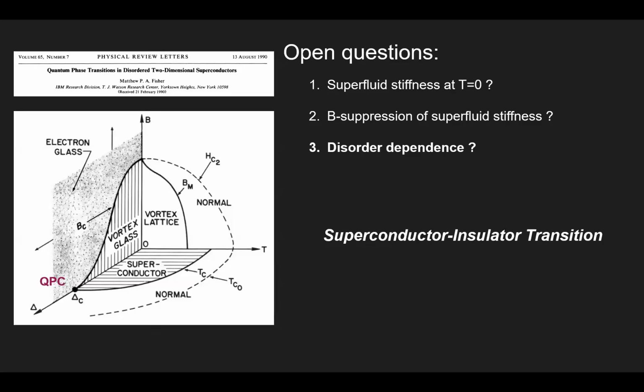And if you look at T equals 0 on the disorder-magnetic field plane, you have this vortex glass phase, and this quantum critical point is somehow pulled all along to zero disorder and forms a line of quantum critical transition, quantum phase transition. Right. And the question I want to address in this talk is how the vortex glass evolves when you start from low disorder and increase the disorder, and look at how your properties evolve at different values approaching the critical point. I want to give you just a glimpse of how it looks in magnetotransport.